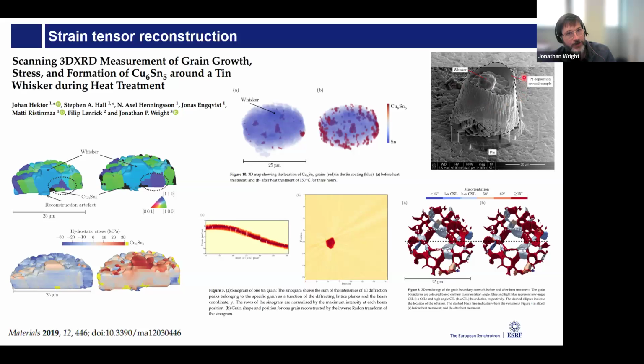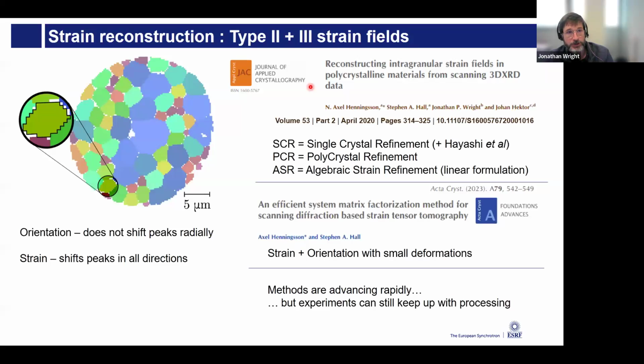So he selected out an area where a whisker was growing, and we have this 3D scanning grain map, 25 microns across the sample, so it's submicron resolution, and there's the hydrostatic stress. So they tried to get out the stress and the strain as a function of position across these grains. And you get, of course, the detailed shapes of all the grain boundaries, you get the misorientations of all the grain boundaries, you have a wonderful richness of data. You see all of the secondary phases and so on. And so we see this as a method that can be applied to many different problems in the future.